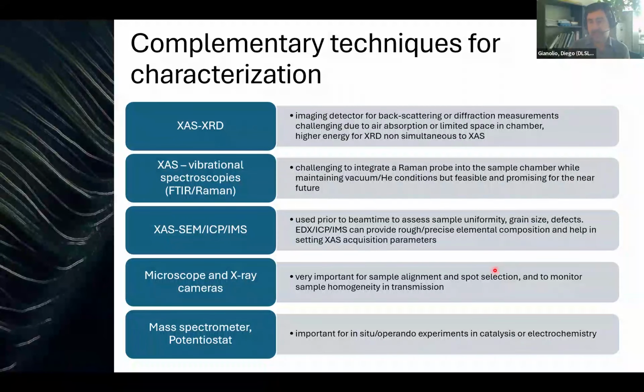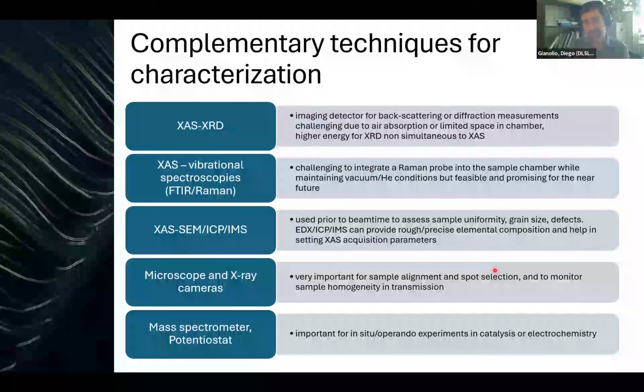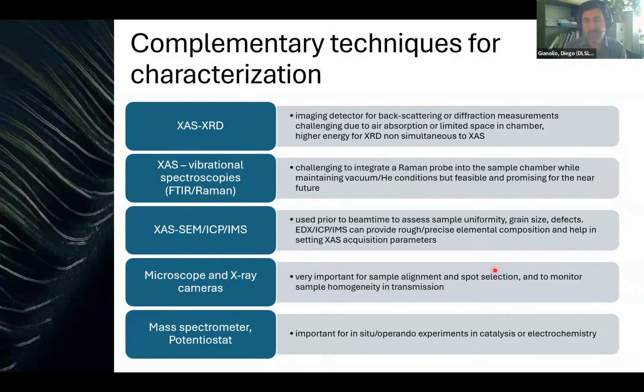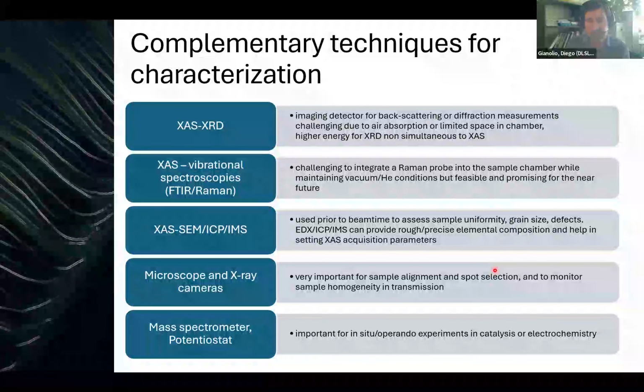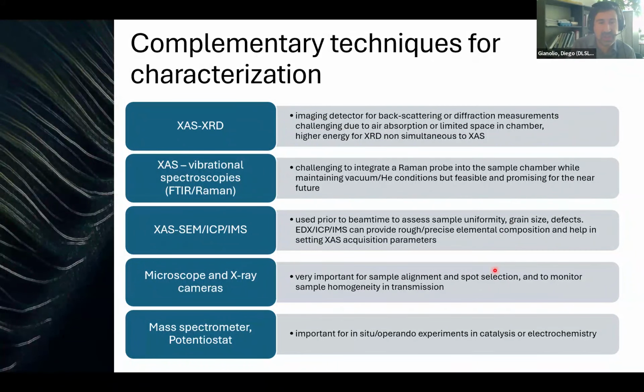For tender X-rays, there is a complication: if you want to measure XRD, normally we measure in transmission through the sample in hard X-rays, but for tender it's hard to go through. So there is a possibility to put the detector in a backscattering geometry, in front of the sample where the beam comes from. But again, you need to consider that working in this controlled atmosphere chamber, there is not much room to fit a diffraction detector in there.